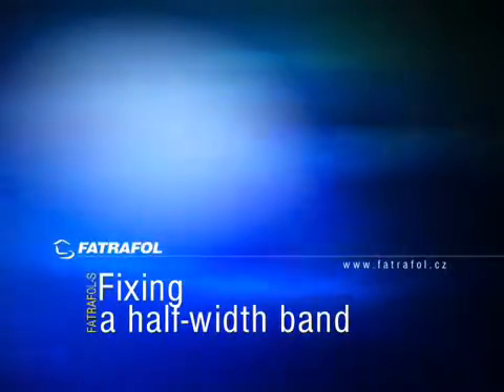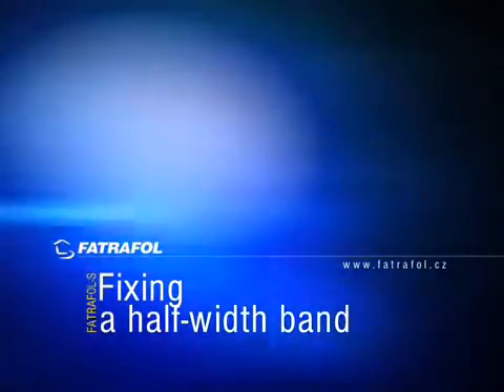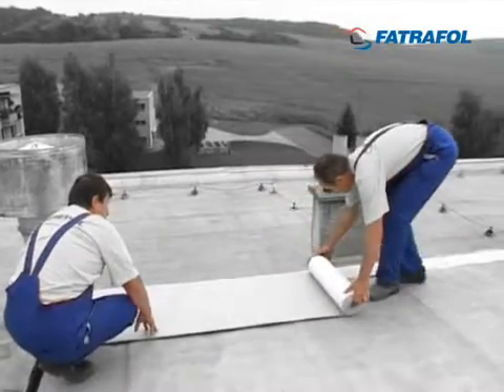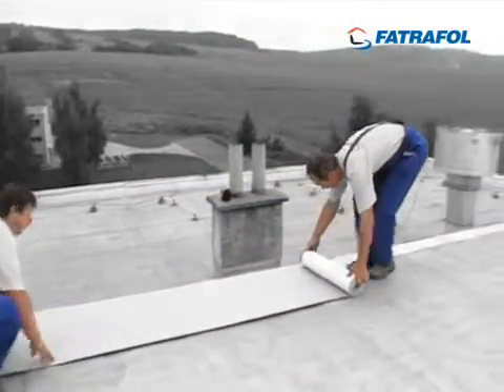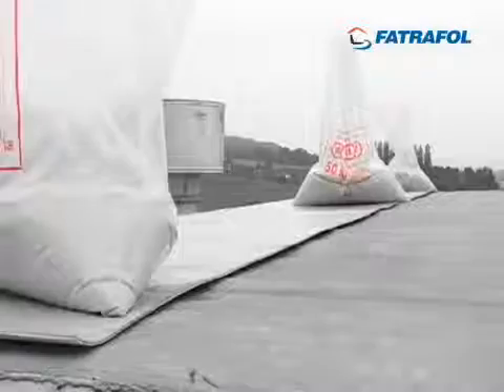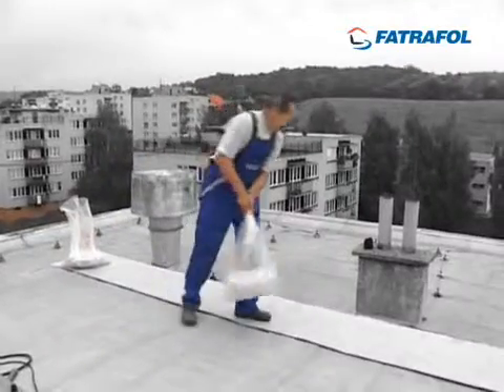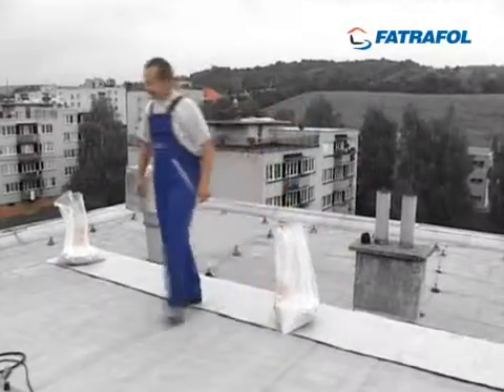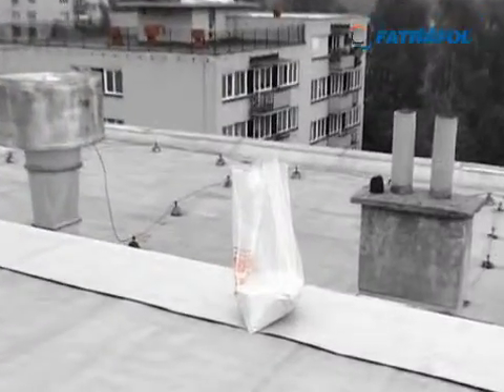Fixing a half-width band. Unwind a half-width membrane band to ensure that the profile fixings are sufficiently covered. Place a load on the band to protect it against wind uplift. Allow the band to lie loosely for at least 20 minutes while its volume stabilizes.